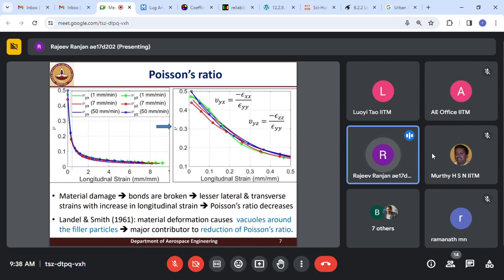At the beginning of loading, it was 0.5, and then as the strain was increasing, this Poisson ratio was decreasing. The reason behind this is that as the material deformed during loading, the bonds which are responsible for contracting the lateral and transverse surface of the specimen break, and then its capability to contract reduces, leading to reducing Poisson ratio as the strain is increasing.